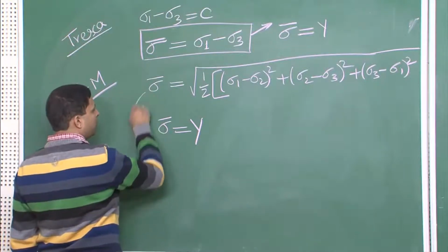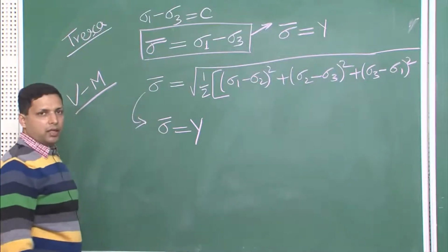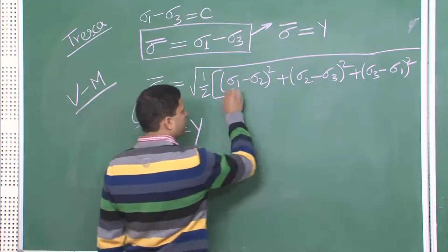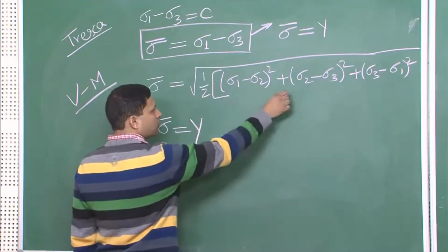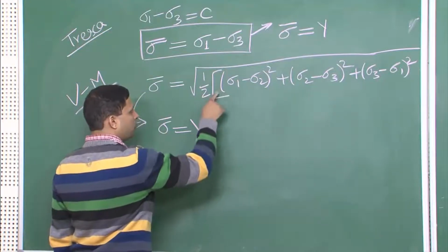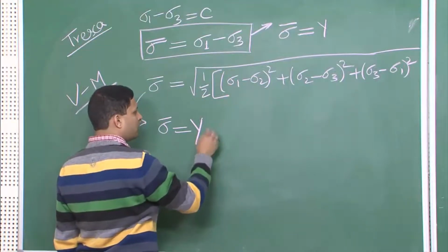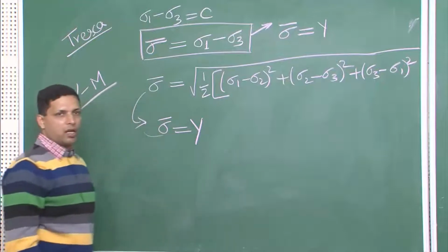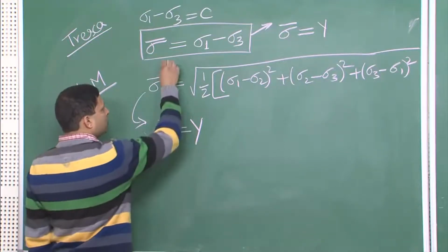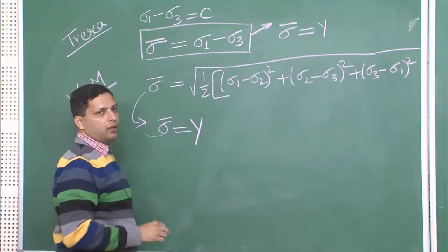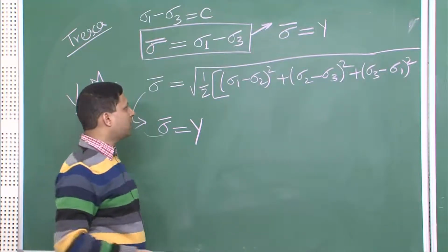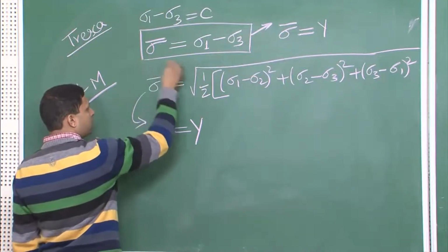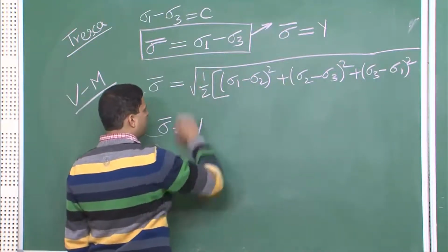Similarly here, if we are talking about a uniaxial tensile condition, sigma 1 is again Y, sigma 2 and 3 are 0, and therefore it becomes 2 sigma 1 squared. So, 2 by 2, and it becomes a square root of sigma 1 squared, and therefore it again becomes sigma bar equal to Y. So, in both of these we see that it does indeed follow the uniaxial tensile condition, and that is one reason why this factor 1 by 2 was put over here.